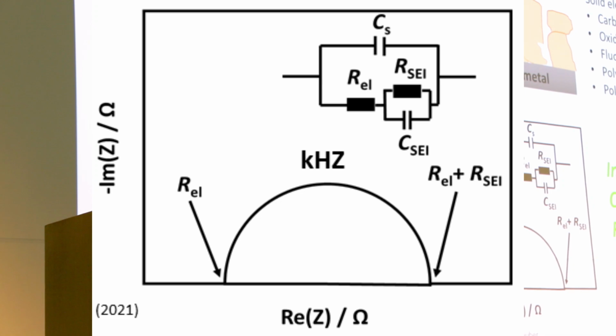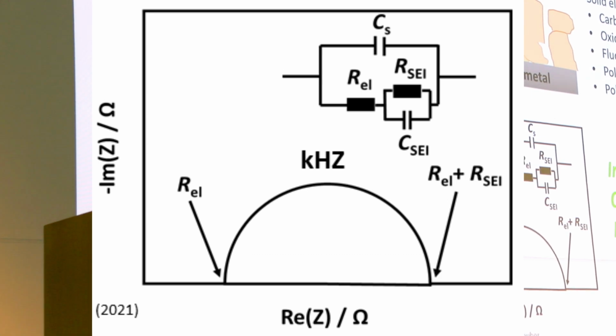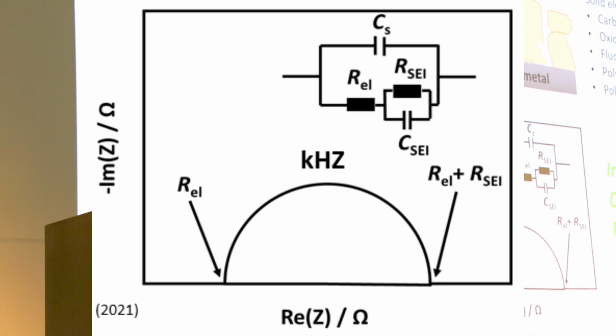So how can we study this material? It has been studied with very many different techniques. If we want to know the thickness of this material, we can try to cut it through with FIB-SEM and see it. But again, we have to do this ex situ. We have to first transfer our material to a SEM, and then we have to know really well how to cut it properly under not so high energy so that we can preserve these interfaces. So this is also problematic, both from the point of view of an ex situ experiment and because of changes upon cutting with our beam.